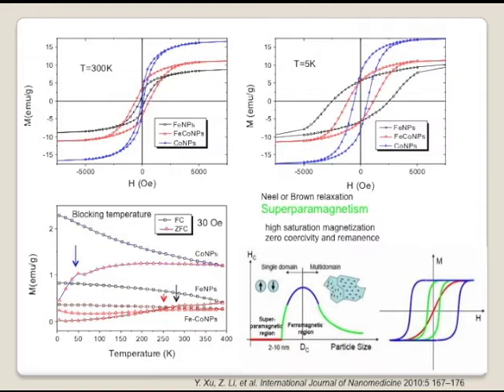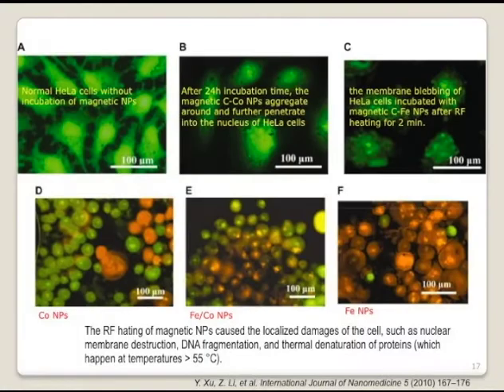Okay, let's see what happens to the HeLa cells. The first image is from the confocal optical microscope. This is just the HeLa cells without incubation of magnetic particles. This is after 24 hours of incubation with the magnetic cobalt nanoparticles. You can see they aggregate inside the cells. You can even find some nanoparticles inside the nucleus of the HeLa cell. It means the nanoparticle is very tiny, 10 nanometers. They can go into the cell and even cross the nuclear membrane into the nucleus.